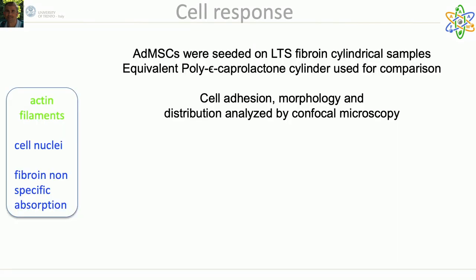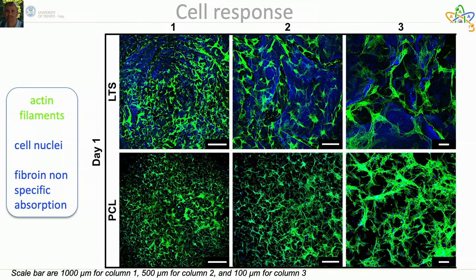The biological response to the fibroin material resulting from the sintering was finally compared to the behavior of similar geometry samples prepared by mold casting of polycaprolactone, an FDA-approved degradable material largely proposed for bone tissue engineering applications. Samples were evaluated using confocal microscopy, capturing images of adhered adipose-derived mesenchymal stem cells at different time points on both types of samples at 3 different magnifications, evidencing cell cytoskeletal morphology, green, and nuclei, blue staining.